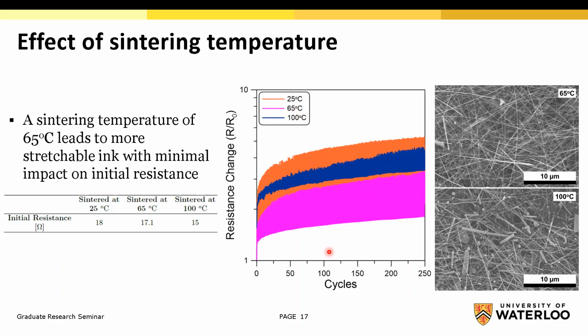So usually people were always sintering their silver nanowire inks at really high temperature to get good conductivity. They were focusing on the conductivity, and they were saying that for high conductivity, we need the highest temperature that the substrate can tolerate. But here we see that lower temperature sintering can give much better stretchable silver nanowire inks. And here you can see the SEM images for 65 degrees and 100 degrees as well. 65 degrees has much better and much smoother nanowires, you can see.